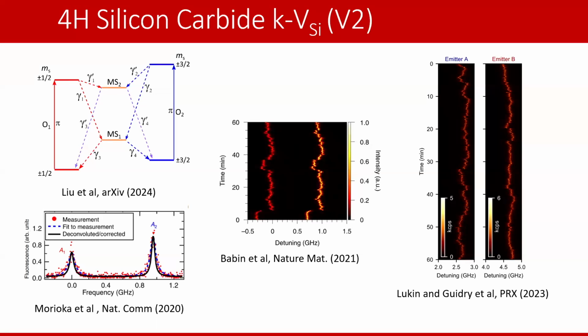But it turns out that with very careful growth and careful electron irradiation to create these defects, you can create relatively stable silicon vacancies in silicon carbide. And so you can see that here. These have then been positioned within waveguides and then eventually resonators. And that's what you see from George's group and from our group here, which is relatively stable linewidth of silicon vacancy within photonic structure.